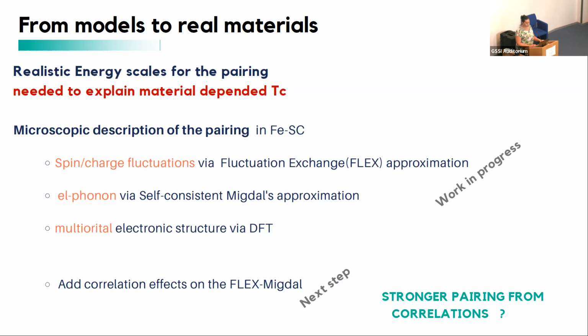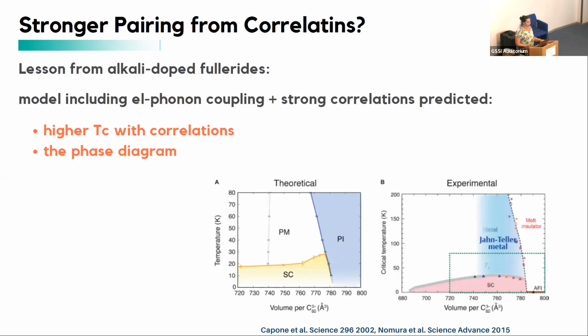The only point that I want to make, and then I'm going to conclude, is why I believe that including correlation in a flex Migdal code for these iron-based superconductors could be useful and lead to a stronger superconducting mechanism. So I think that this is possible, and my inspiration comes from the alkali-doped fullerides. In this system, you have a model in which you can include electron-phonon coupling and strong correlation that actually predicted that you would have a higher Tc with correlation, and the phase diagram that you could have with correlation effect. And it's remarkable the agreement between experiment and theory in this case. And why here was the effect of correlation beneficial for superconductivity?